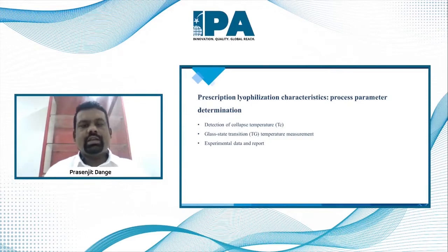The collapse temperature is one of the critical parameters for setting up the lyophilization process, because at this temperature the material either melts or gets softened so that it cannot support its own structure and begins to flow. This is the reason the substance should always be kept below the collapse temperature while doing the primary drying in the lyophilizer. However, a process that is too far below the collapse temperature will lead to an unacceptably slow progression of the complete cycle. Therefore, it is important to know the value of the critical temperature.